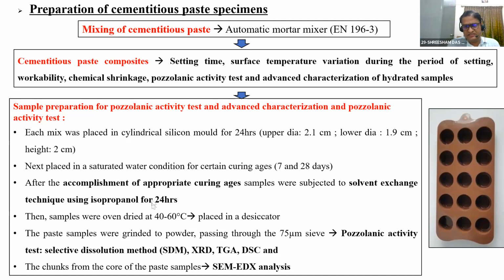For the paste, you can see on the right side, this is a silicone mold normally used for preparing chocolates. We have prepared small size specimens: diameter 2.1, lower diameter 1.9, and height 2. We have cast small specimens following all the standard casting procedures, and after certain days, that is 7 days and 28 days, they were subjected to advanced characterization studies.